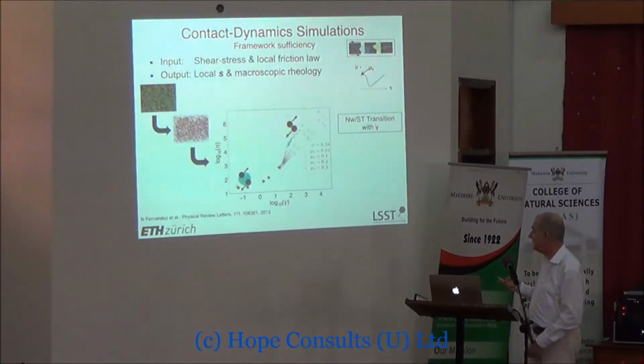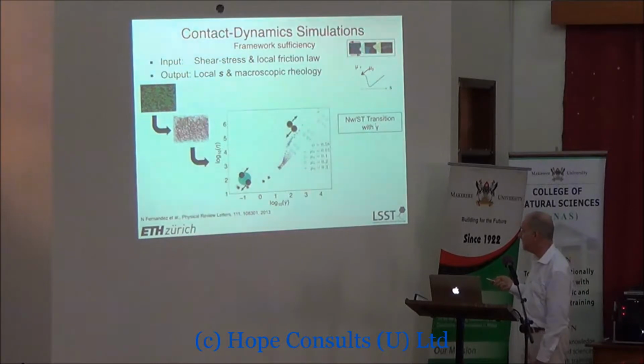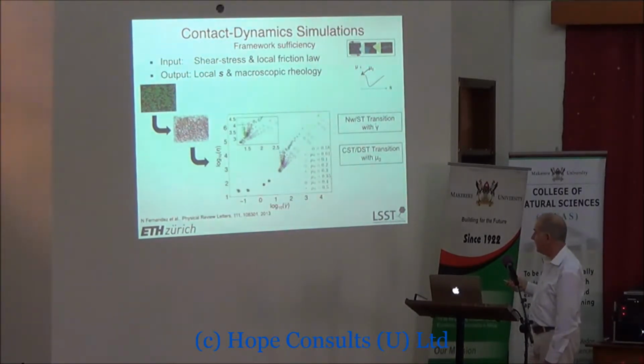And we managed to use that, just those two behaviors, hydrodynamic and boundary, to explain this discontinuous and continuous shear thickening. As you see, we have the Newtonian flow reproduced down here. So this is the model based on lubrication theory, and we could reproduce the continuous shear thickening as we went to higher speeds. But what we also found is that when we went to very high speeds, we could actually reproduce the discontinuous shear thickening as well. And by changing the friction coefficient, we could move from continuous to discontinuous shear thickening.